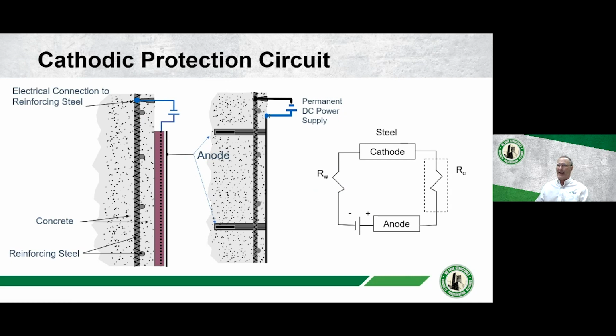In reality, what we are doing is you have this reinforcing steel, and it's encased in concrete, and you're either going to place an anode on the surface, or you'll place an overlay and embed it in the overlay, or you're going to install the anode into the concrete, and so the anode will throw current to the reinforcing steel from inside. And when you do that, you have some wiring that's involved.